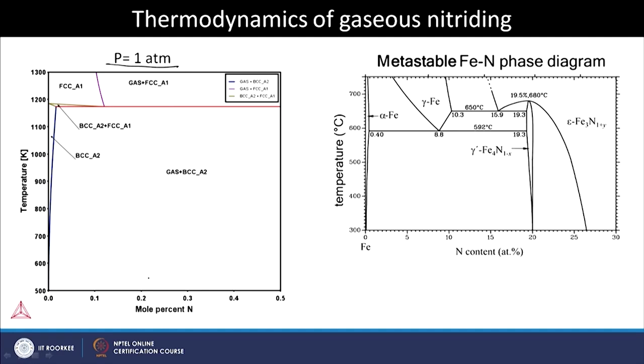we see that we get a very small amount of nitrogen dissolvable in BCC iron — that is, the ferrite. The maximum solubility is given by this line. We do not see any other iron-nitrogen compounds, which are known from the metastable iron-nitrogen phase diagram, where we have two iron nitrides. The amount of nitrogen dissolved in ferrite from N2 gas is much lower than what the phase diagram allows. Now we want to see how these iron nitrides can be realized by using ammonia gas instead of N2 gas as the nitrogen source.